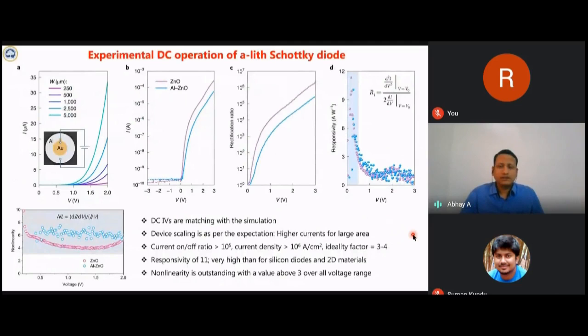So now this is the experimental data, DC. So we will start with the DC. These are the IV characteristics for a forward bias for different widths. So this is 250, 500, and the largest was 5000 micrometer. And when this data is plotted in log scale, you see this is a reverse bias current, which is of the order of 0.1 nanoampere, and this is the on current, which is 0.1 milliampere.